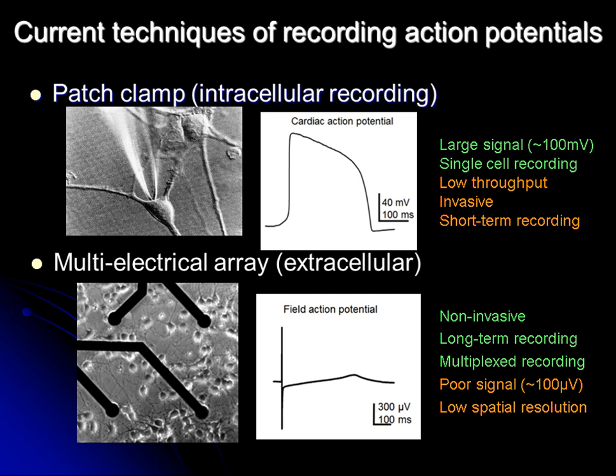It also has a low spatial resolution. If you look at the shape of the recorded action potential, they look vastly different. For the cardiomyocyte action potential, if you use intracellular recording, you record one single upward peak. On the other hand, if you use extracellular recording, you record a biphasic peak. The peak goes up and then goes down, and they do not look alike at all. The reason is the extracellular recording is the first derivative of the intracellular recording. So quite a few labs are trying to combine these two techniques: how we can achieve non-invasive, long-term, multiplexed intracellular recording.